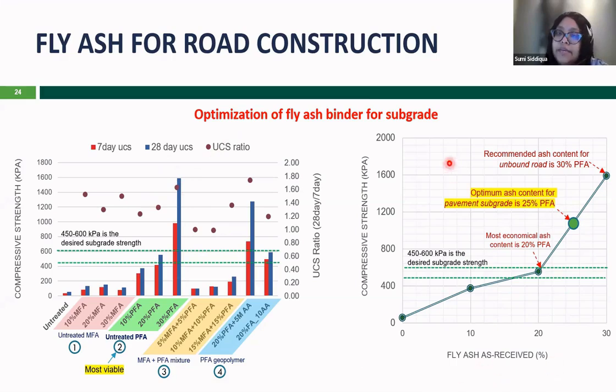Now, if you look into that behavior in terms of the compressive strength and the fly ash as received, we are looking into our desired value for the subgrade strength, which is between 450 to 600 kPa. And now we see this 20% one is the most economical ash content, which is 20% precipitator fly ash. And then we see the optimum ash content for pavement subgrade is 25% based on our data. And we also recommend ash content for unbound road is 30%, because we don't have to go for the final development of the roads. For unbound, unpaved roads, we can use 30% fly ash.